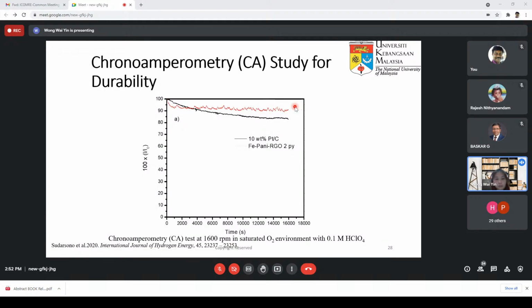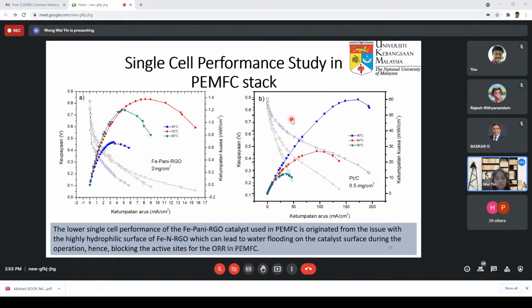On the aspect of durability, a chronoamperometry study was performed, and it showed that the Fe-Pani-RGO retained about 90% of the current after a 16,000 seconds study in the same environment. It is more superior compared to the Pt/C, which actually degrades faster in terms of the current density.